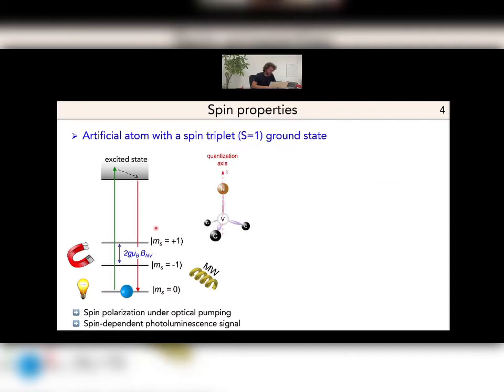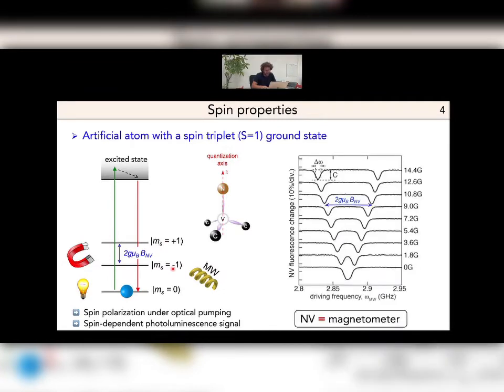If now there is a magnetic field applied at the location of the NV defect, as I mentioned before, there is a Zeeman effect that will lift the ms equals +1 and -1 degeneracy. And if you now record electron spin resonance spectra while changing the magnetic field, you will see, from the bottom to the top as you increase the magnetic field, the splitting of the ESR lines. And this splitting is directly proportional to the magnetic field felt by the NV defect. More precisely, this is what is written here, B_NV, because the component that is measured is the magnetic field projection along the quantization axis of the NV defect, which is defined by the direction linking the nitrogen and the vacancy. So just to show you that the NV defect behaves intrinsically as a magnetometer.